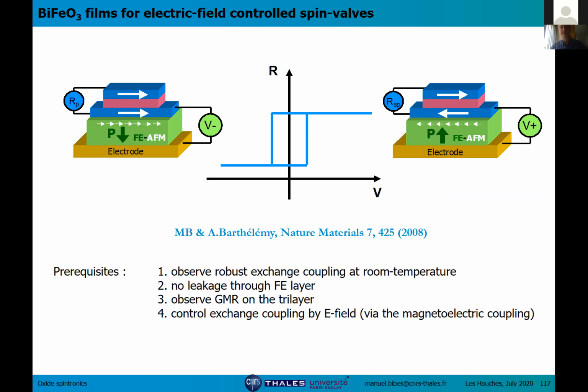So this is not easy to do. You need a lot of conditions to achieve that. You need to have a large exchange coupling between your multiferroic and your ferromagnets. You need to avoid leakage across the ferroelectric. You need to have GMR or TMR in your spin valve. And of course, you need to be able to control the exchange coupling by electric field through the magnetoelectric coupling in the multiferroic material.